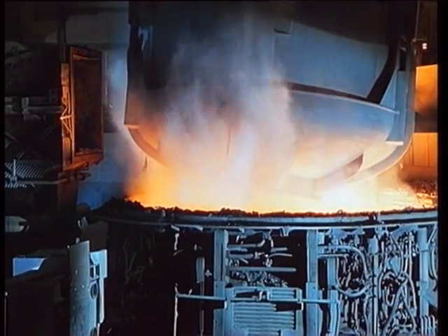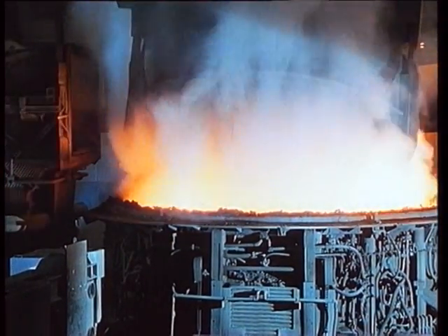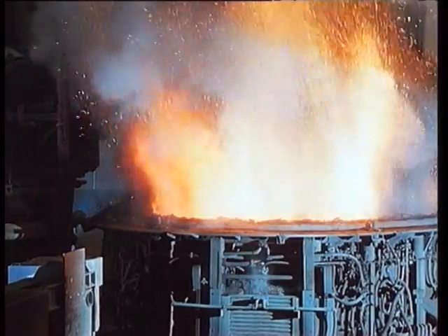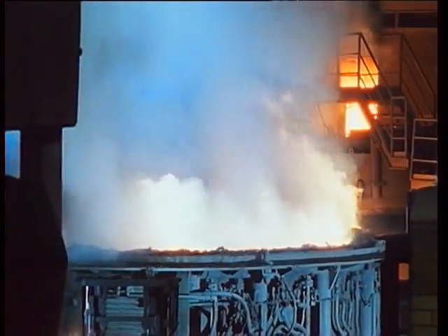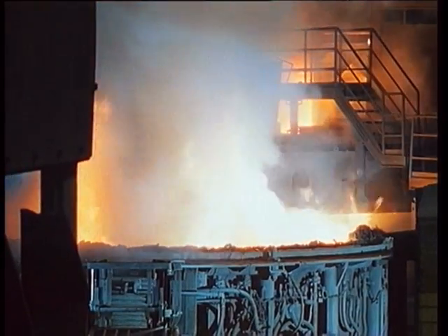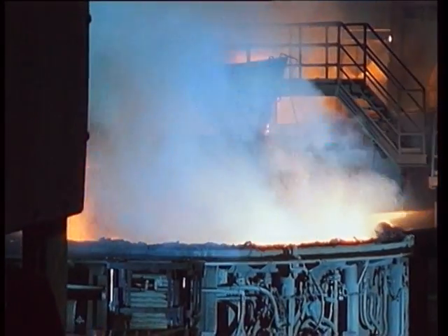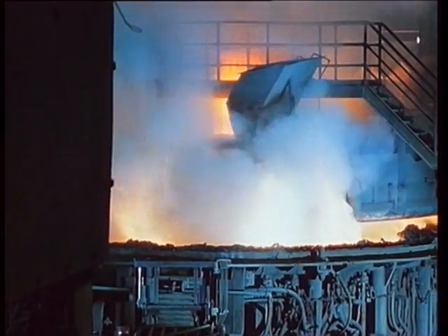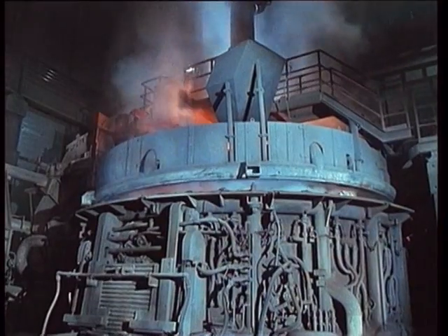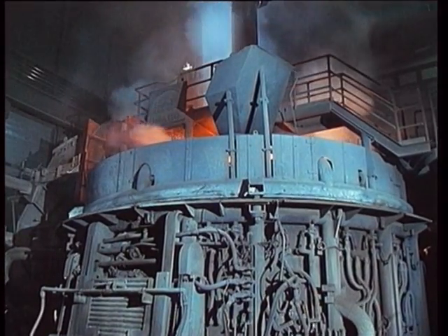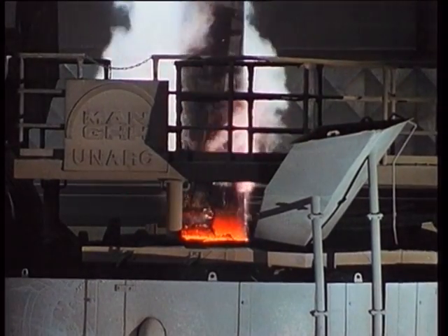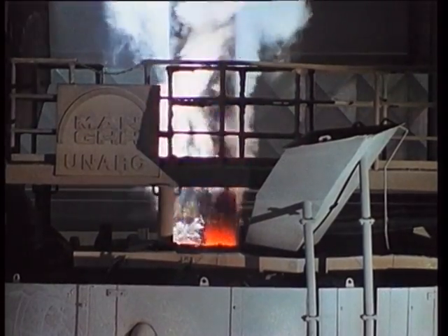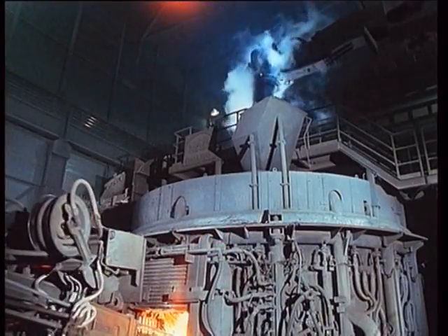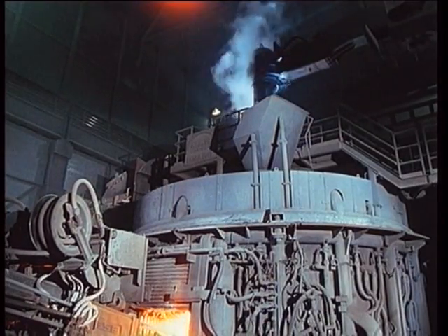Scrap metal and slag-generating materials are poured into the already hot furnace. Impurities partially burn away during charging. Then, the heavy lid closes the furnace tightly. Graphite electrodes are lowered close to the surface of the charge. A high current flowing through the electrode arcs over the metal and heat is generated by resistance. Temperatures as high as 3,500 degrees Celsius melt the metal quickly.